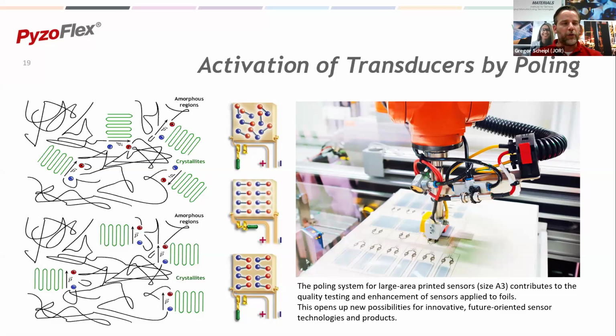And we have for standard geometries and standard substrates a yield of more than 99% with a very high remnant polarization up to, I think, 75 millicoulombs.